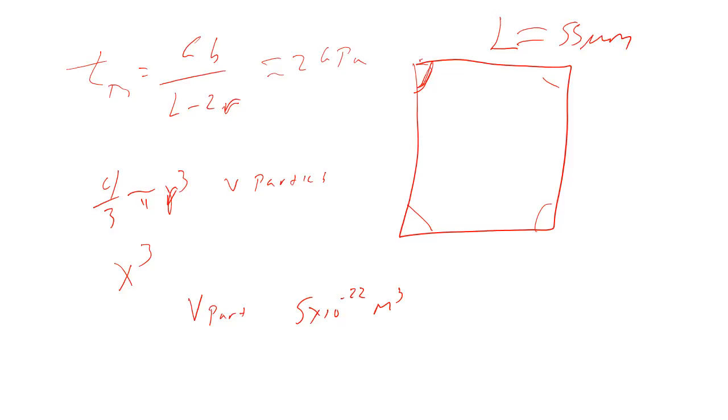2 GPa. This assumes no cutting; this is the equation for bowing out. The 50 nanometer particles are small. If you assume there's cutting, you can calculate the shear strength and the APB energy. But it's a lot more straightforward if we just assume that we're going to be bowing around them. Then this is high.